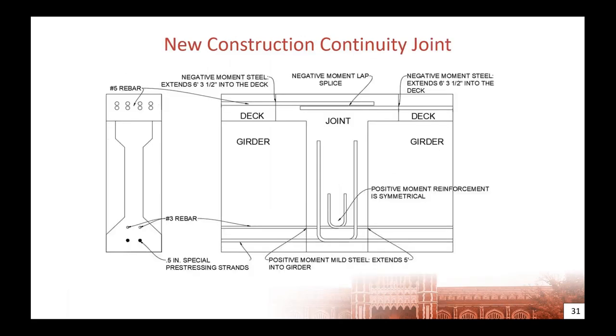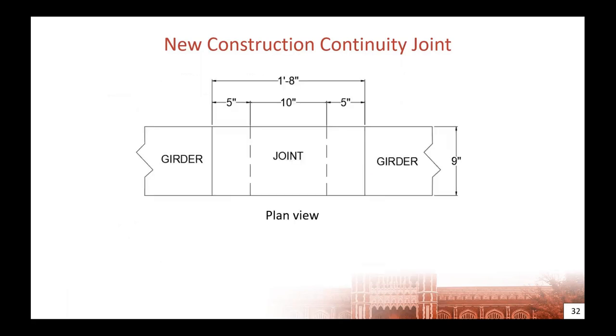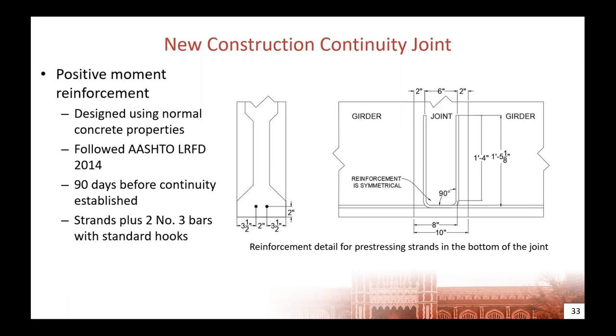We examined two joint details, as I mentioned, one that was intended to represent new construction that utilized the pre-stressing strands in the beams as our positive moment connection in the bottom, and then had the reinforcement from either side of the deck coming into a splice in the joint. It was a 10-inch wide joint to match what was done in the field in Oklahoma. We had an additional portion of the deck replaced with UHPC to ensure we had a proper splice in the deck. And for these connections, initially we started out designing our reinforcement in the positive moment region using conventional concrete properties and the methods of AASHTO LRFD 2014. We let the girders cure for 90 days before establishing continuity so that we could use the lower strength requirements in the AASHTO LRFD specification.